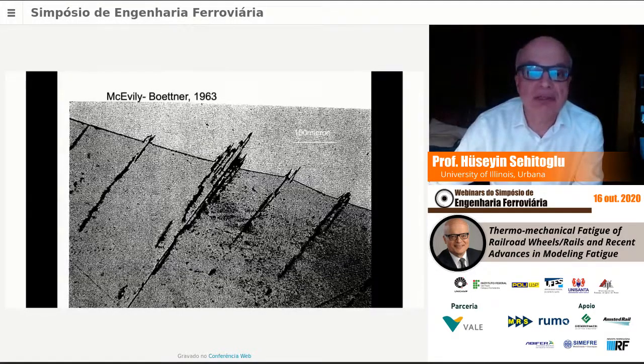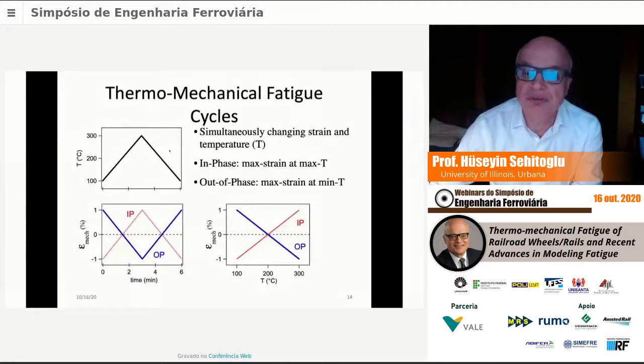Now, McEvily and his group also show that these slip bands cannot penetrate easily through some grain boundaries, and there is a large stress concentration at the boundary, and this is the cause of fatigue cracking in a number of materials. Particularly these boundaries, as shown here, are twin boundaries.